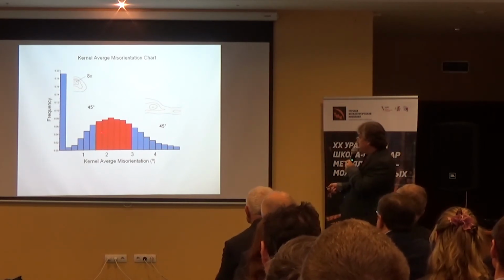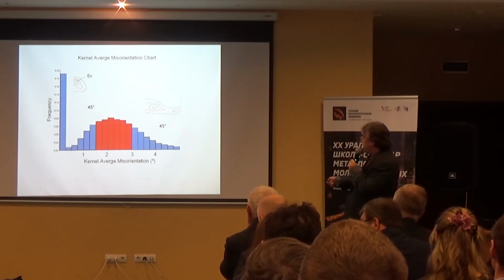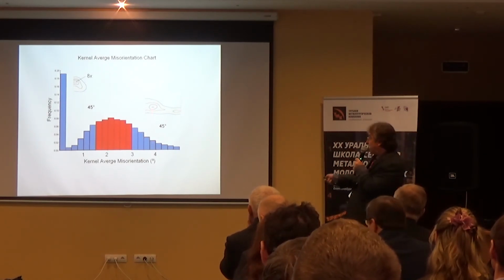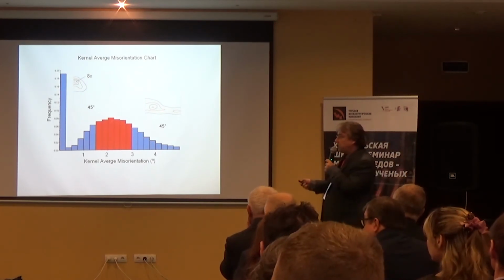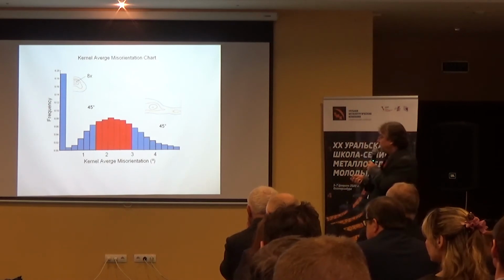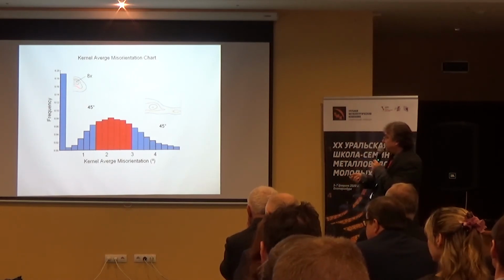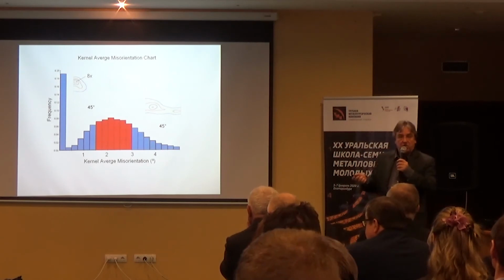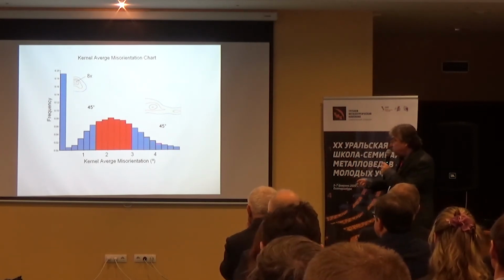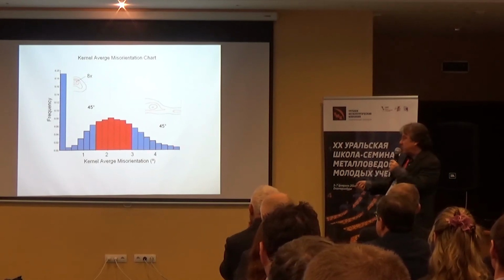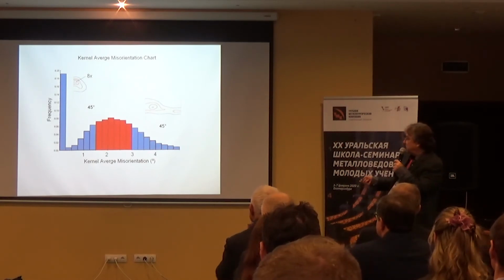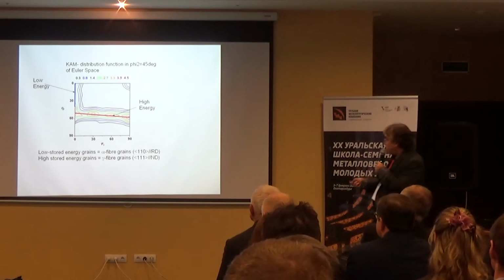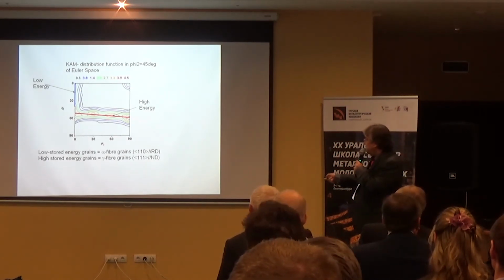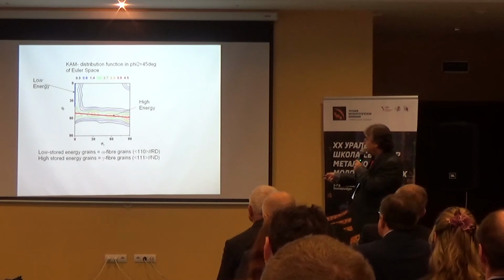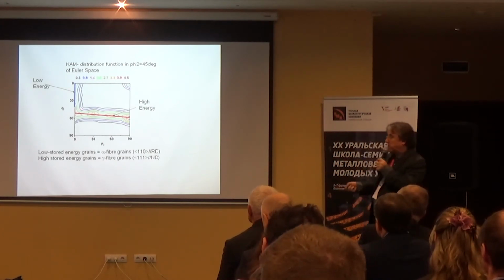But what is interesting to see is that if we take the partition here at the high end tail, these are the gamma fiber orientations. If we take the partition here at the low end tail, these are the alpha fiber grains. So KAM is a measure of stored energy, of dislocation density, of geometrically necessary dislocations. So, okay, that's my argument here. Here we have a high energy region, and here we have a low energy region.